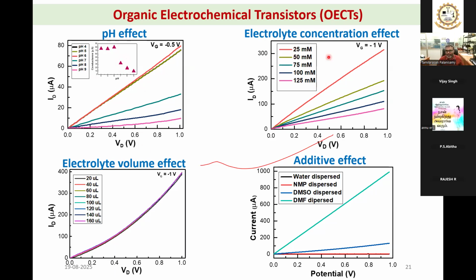On the other hand, if you see the electrolyte concentration, that also can affect. The reason is your body may have different concentrations of electrolyte. Particularly, we have used this device for sweat glucose sensing applications. So obviously, sweat will have different concentrations of salt depending on our body's hydration and the outside environment. So we have tested the transistor with different ionic concentrations, so ionic strength. Obviously the ionic strength changes the conductivity. So when we use this transistor, first we have to analyze the ionic conductivity, then we have to find out the glucose concentration. So it has to be offset. So that's what we would like to tell you.